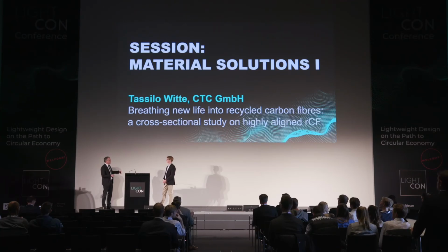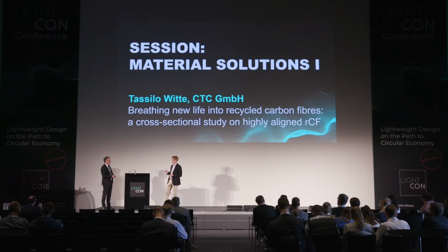I don't see one. I have a question. Have you calculated the energy saving, because you need energy for the pyrolysis and so on, compared to the new material? We know very clearly the difference in processing, which is basically very little. The biggest challenge is to get the proper data on the impact of the pyrolysis process itself. If you talk about cumulative energy values, so KEA or KEV, a carbon fiber has an embedded energy of between 220 and 240 megajoules per kilogram. A recycled carbon fiber, as stated by the companies who do that, currently has an embedded energy of about 30 to 40 megajoules.